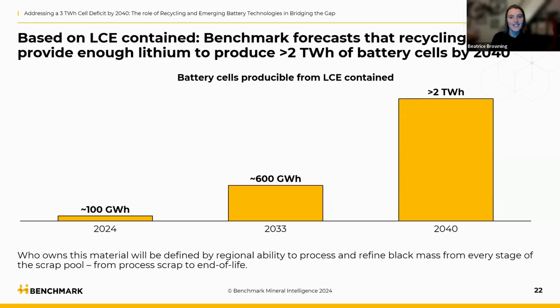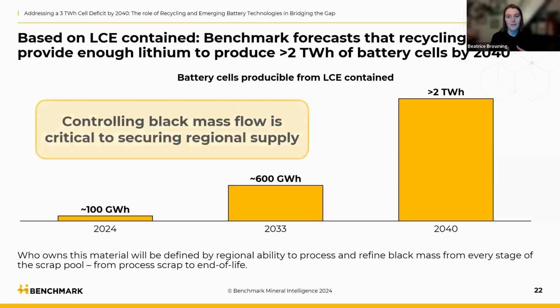And then finally, considering lithium contained within the scrap pool and how this lithium could be translated into battery cell gigawatt-hour volumes, it's clear that lithium from recycled sources could be utilised in cell manufacturing to produce around 2 terawatt-hours of battery cells by 2040. In order for each region to make the most of the lithium contained within this localised scrap, controlling material flow is essential. So with black mass generation being a key part of the supply chain, controlling black mass flow is going to be critical in securing regional supply.